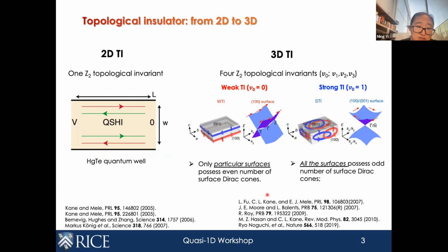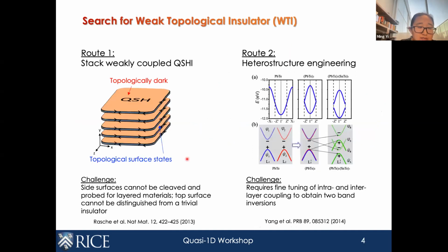As Fan has already introduced, experimentally, the vast majority of compounds that we have identified as TIs are strong TIs, and it's really challenging experimentally to identify weak TIs for the following reasons. There are different routes to realizing a weak TI. One way is to stack weakly coupled quantum spin Hall insulators, where the gapless boundary modes can then couple together to form these topological side surfaces. But experimentally, it's difficult to confirm that these are actual weak TIs, because these samples are very hard to cleave on the side, which makes them not really accessible to probes like STM or ARPES.